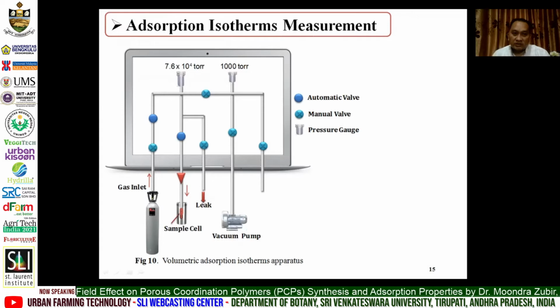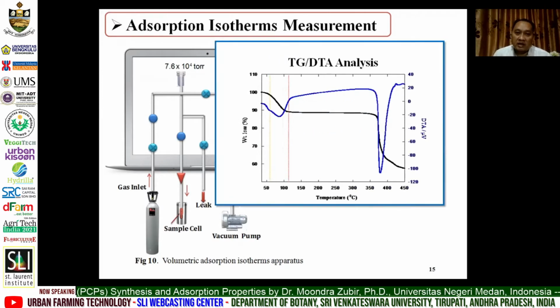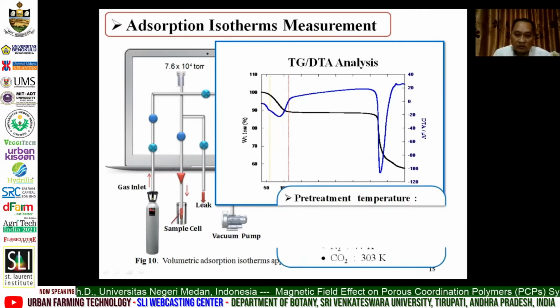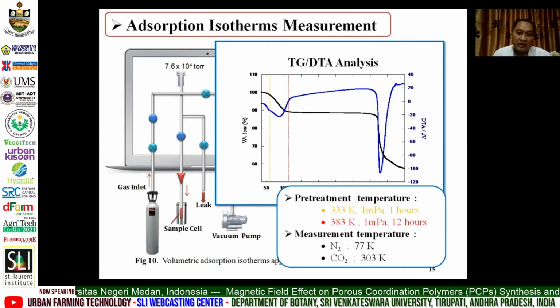And this is the adsorption isotherm measurement. We use the volumetric adsorption isotherm apparatus, and before the adsorption isotherm measurement, based on the TGDTA analysis, the solvent was removed around 110 degrees Celsius. So before the adsorption measurement, we do the pre-treatment temperature in 2 stages.